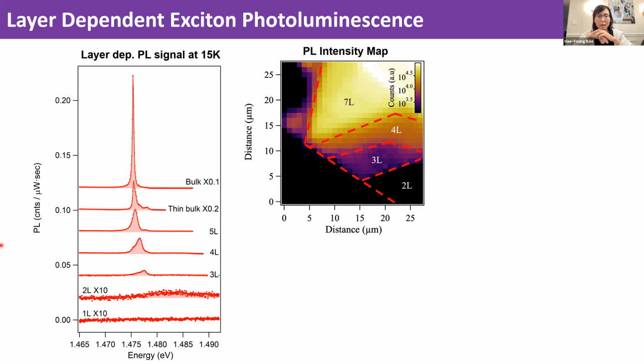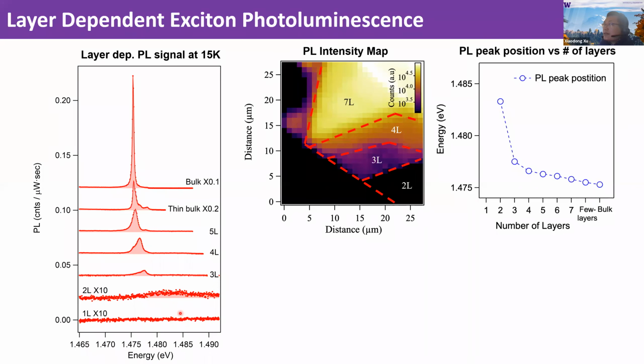Oh yeah, so I'm really confused. Because your PL intensity, when you're showing the LDA calculation, it's a function of layer dependence. You said it really matches quite well. Where are the correlations? So what I said, I didn't say the intensity matches, but what I'm trying to say is the trend we observe. The trend observed here is that when I reduce the layer thickness, the PL intensity drops, especially when I go to bilayer, it drops dramatically by orders of magnitude. And with the monolayer, there's no PL observed. Okay, that's number one. Number two is we observe this blue shift of the exciton resonance all the way to bilayers. So those are the two features observed: the PL intensity drops dramatically when I reduce layer numbers, and the second is there's a blue shift.